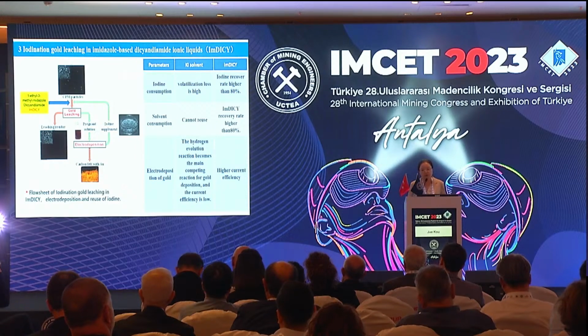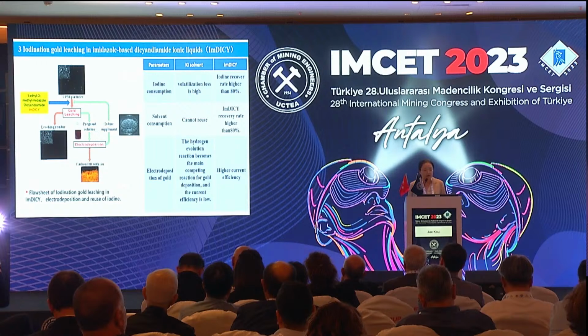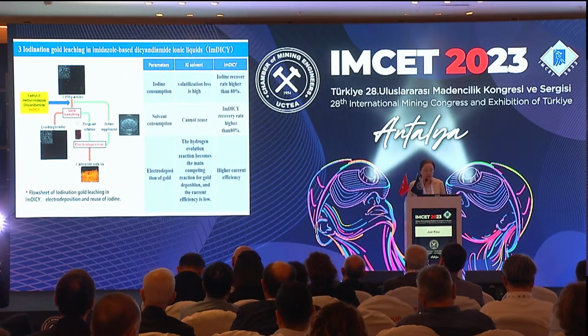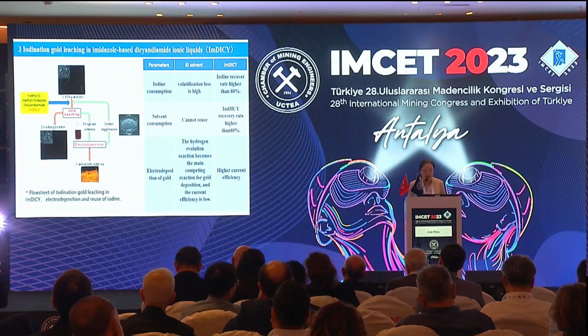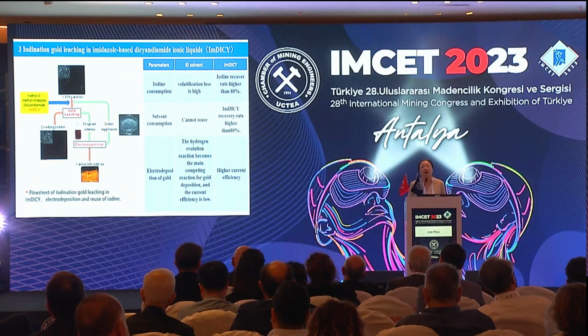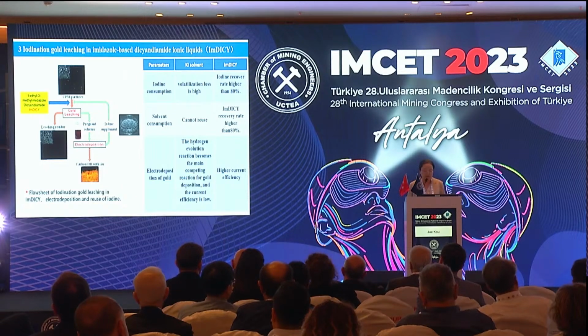First of all, we don't use water. We use ionic liquid as the solvent. We dissolve the iodine in the ionic liquid to prepare the gold leaching lixiviant. During the gold leaching, we collect the pregnant solution. To further recover the gold from the pregnant solution, we use electrodeposition. We use carbon felt to deposit the gold on the surface.